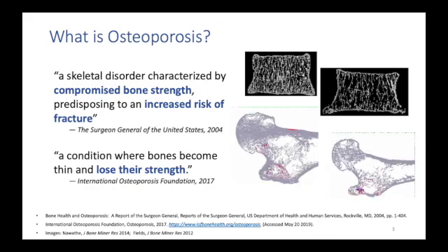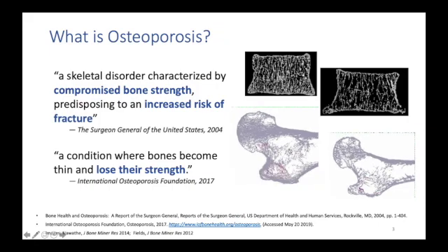What you see in the stronger, healthier bone is there's lots of trabecular bone and cortical bone to share load. So if there's failure locally, other tissue can step up and take the load. So in order to fail the whole bone, you actually have to fail a lot of tissue. But with the weaker bone, there's much less tissue, and once some of it fails, it's over. There's no redistribution of anything. So you've lost structural redundancy. And so we believe that's a very important element of bone fragility when you get older.